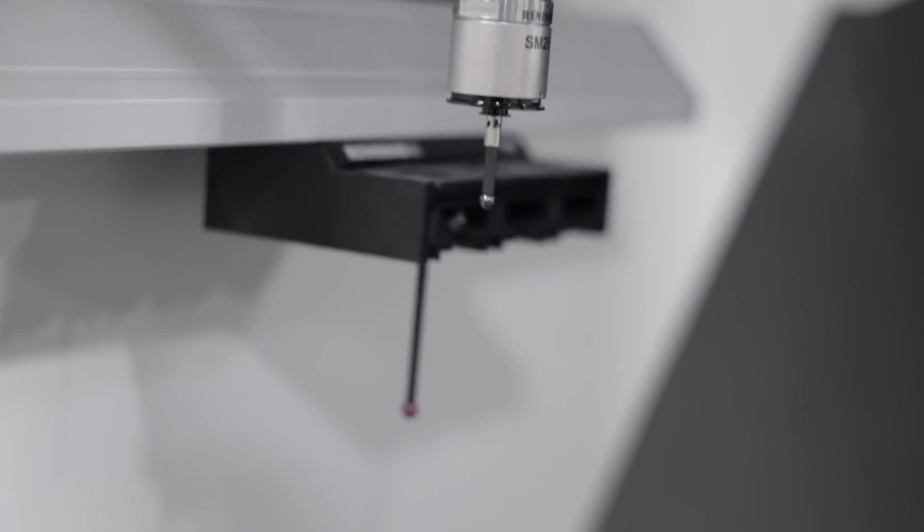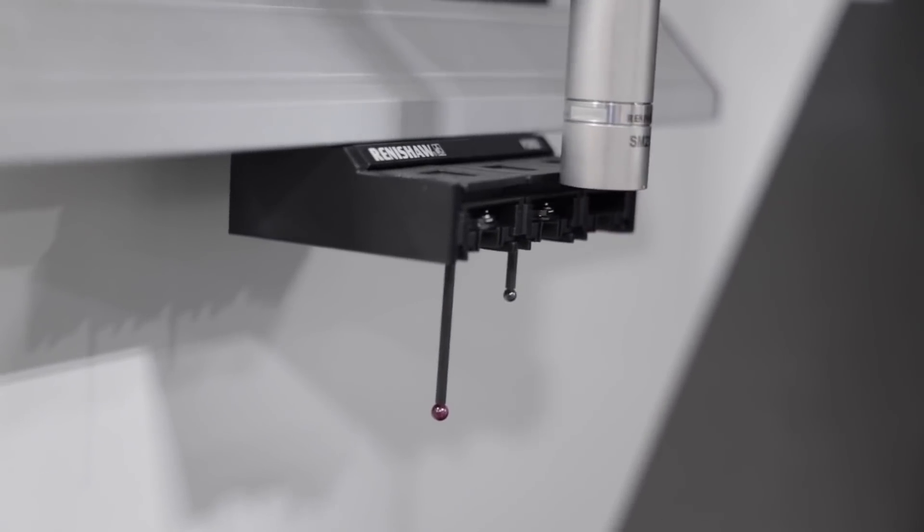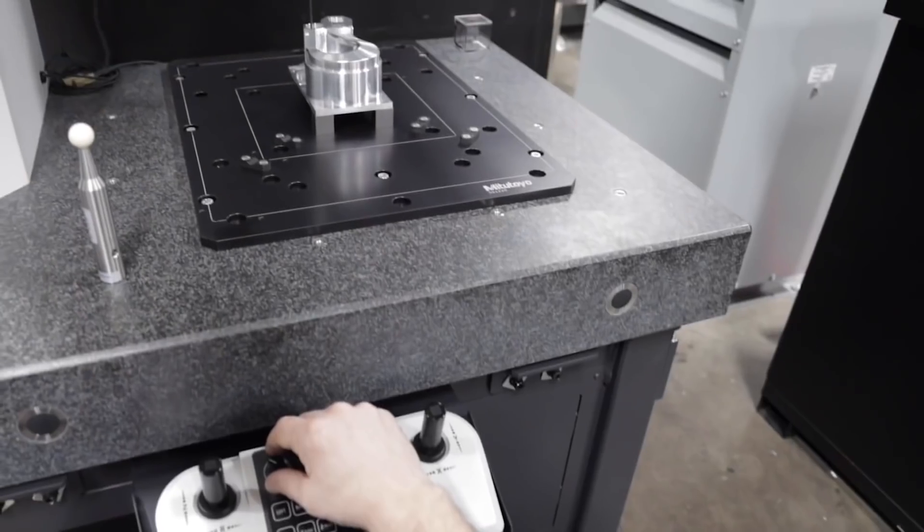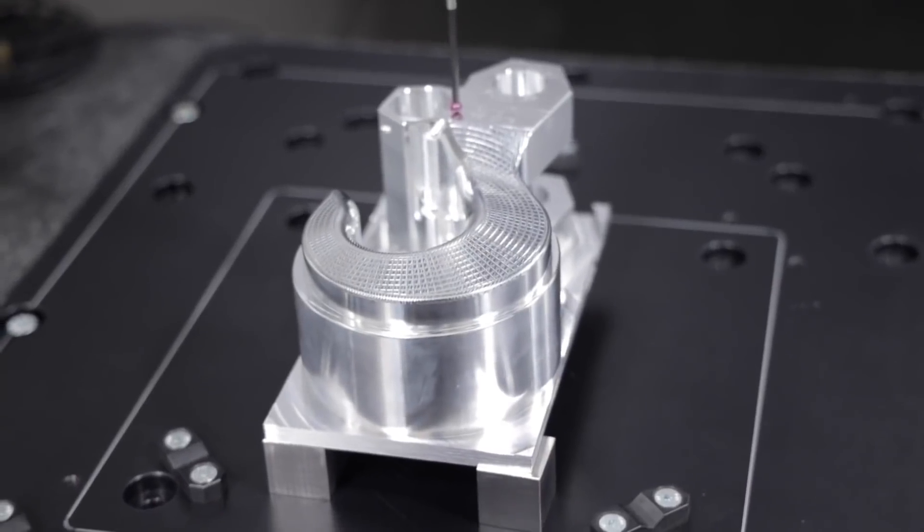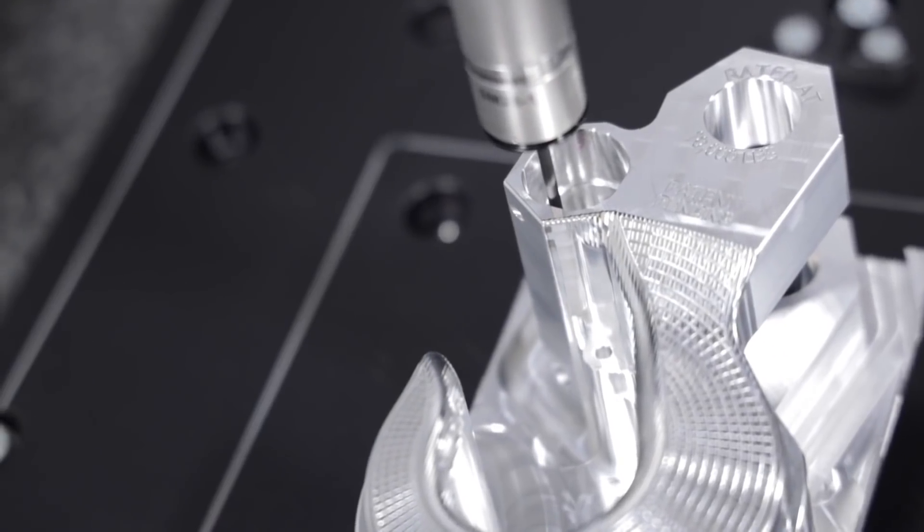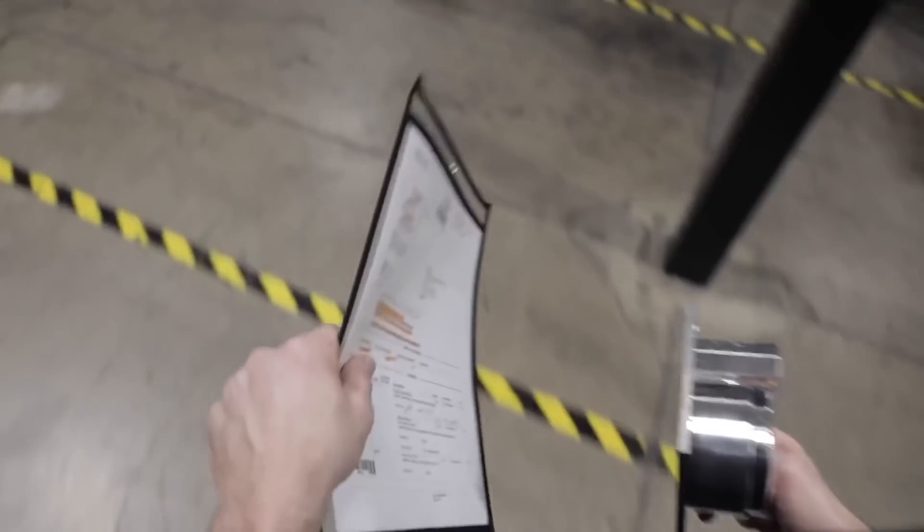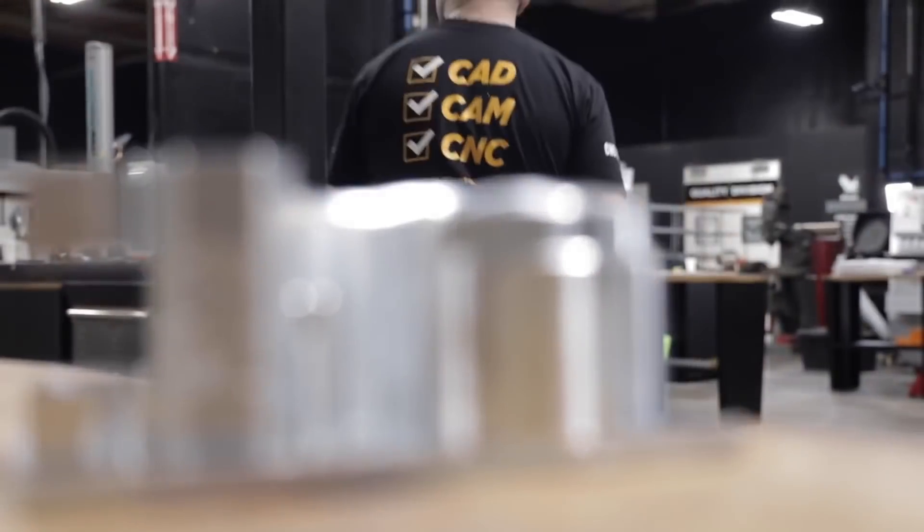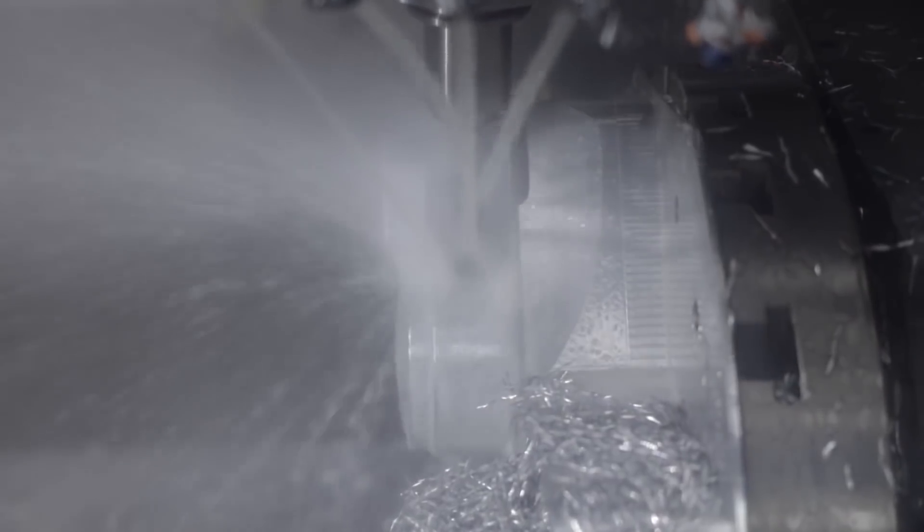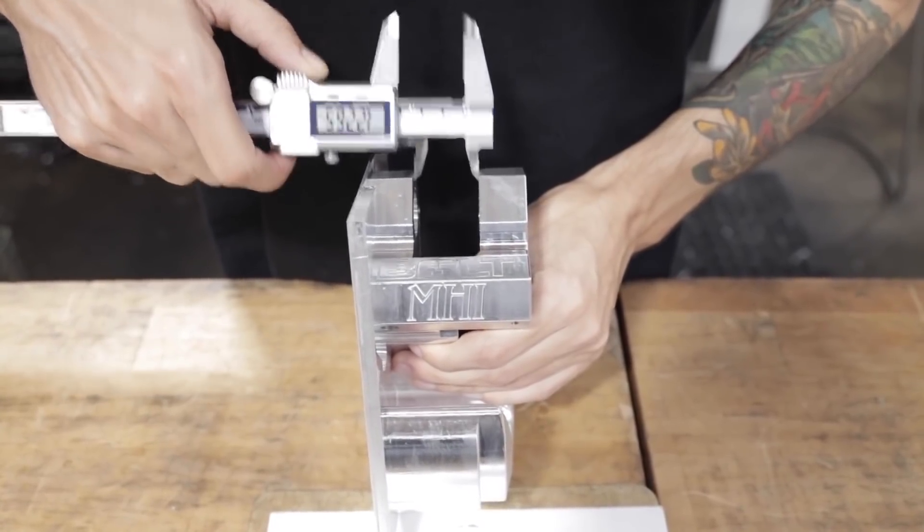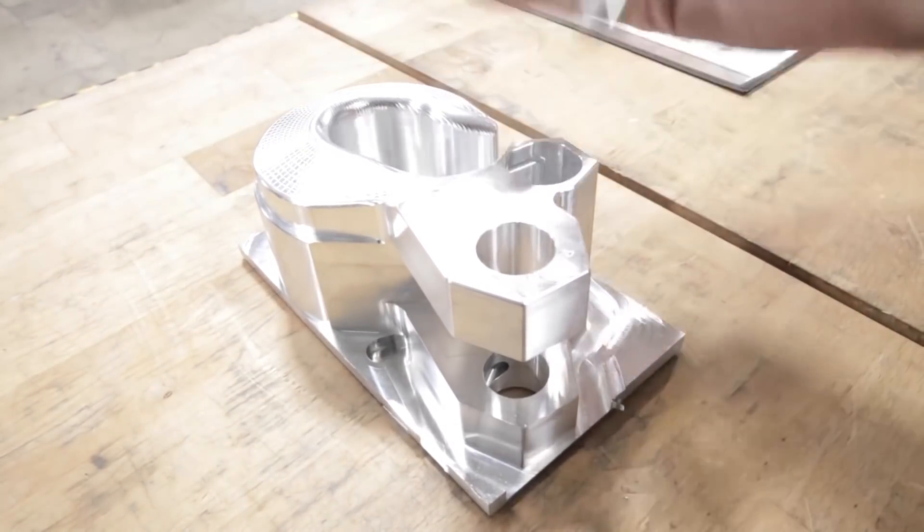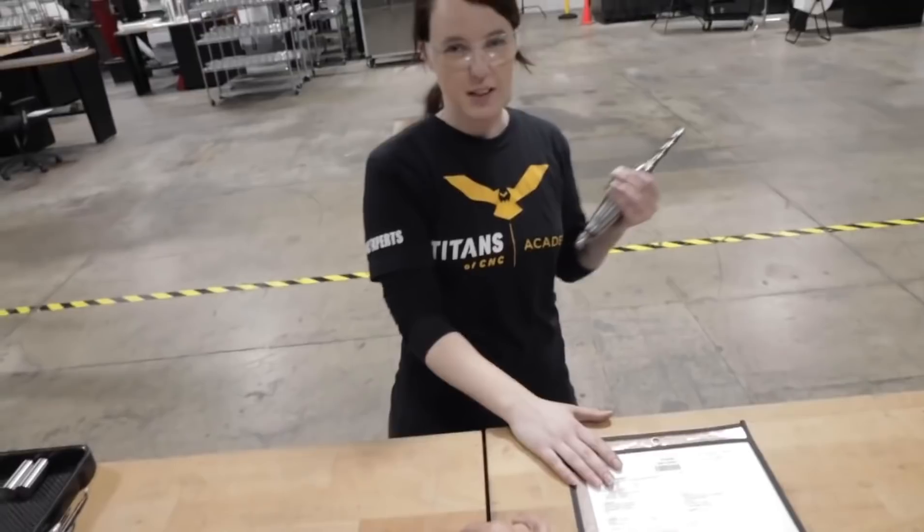If we know the thickness of our Type 2 or the thickness of our Type 3, we would make the thread larger based on those tolerances. If you look at a regular tap, there's G values and H values. G designates a ground thread, H designates the pitch diameter. You can get these taps and they'll be like H3, and H3 you might just use for a standard thread that doesn't get anodized or it's getting plugged. But if you're actually putting anodize based on the tolerance, you'll go up to an H7, which will be a larger tap. It'll add three thousands to three and a half thousands to the diameter that's being cut.